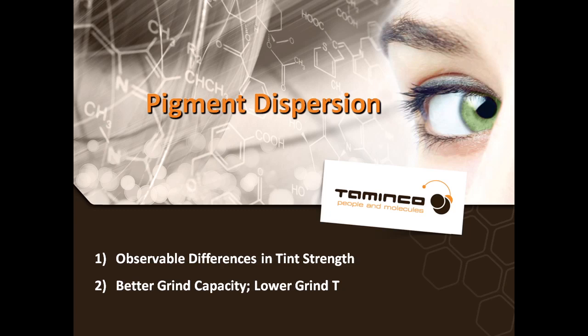I think many career paint formulators are familiar with the fact that multifunctional alkanolamines act as supplementary pigment dispersants. Certainly when you switch from ammonia to any multifunctional amine, you will be able to reduce the level of your pigment dispersants significantly. You'll also have an easier time in the grind because you won't have ammonia evaporating from the grind, and a number of other ergonomic benefits as well.